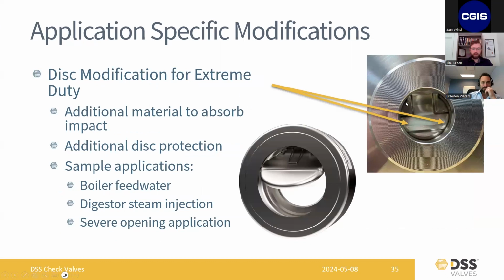And then we can actually beef up the disc of our valve as well. So if you've got applications where you're concerned about the disc going from closed to fully open, we can actually put these stops, these internal integral stops on the backside of the disc. And that's just extra sacrificial material that helps the disc as it opens, protect it from damaging itself when it opens into the body.